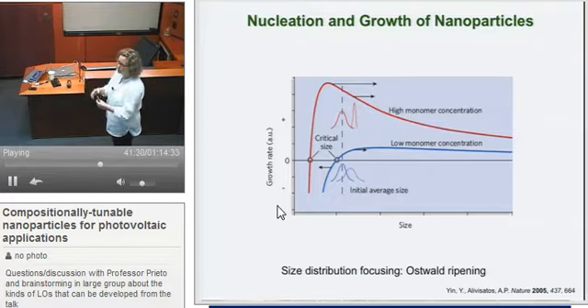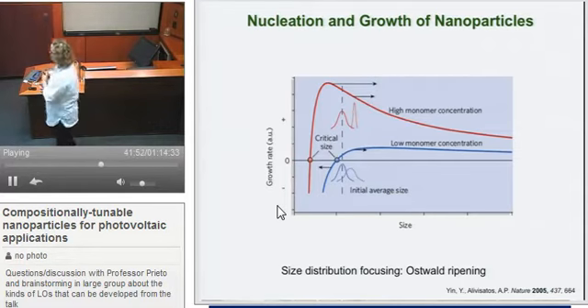So the point is that you can control the equilibrium of these particles growing versus dissolving by the concentration of the precursors in solution and the size of the particles. So you can sort of toggle back and forth by adding a ton more monomer to make your particles fall on this red line, or doing your reaction at low monomer concentrations where you'll be on this blue line. So this paper in and of itself, I usually spend, say for my nanotechnology class, almost a week on. And this can tie to the basic LaMer method.